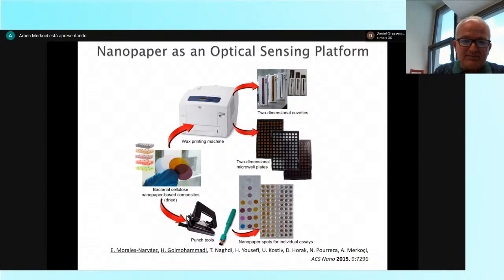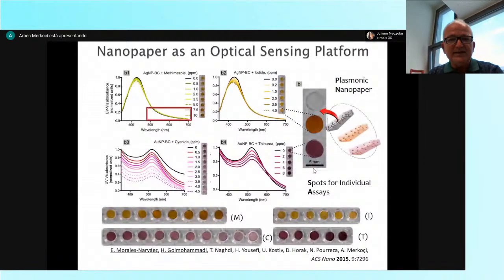So to make some simple optical measurements, we need to set up some cuvettes, like two-dimensional cuvettes or two-dimensional micro-well plates, in a way that we are able then to detect, like in an ELISA, in micro-wells, several papers and do some measurements. And in fact, we did some simple measurements with some compounds, like, for example, methimazole, iodide, cyanide, thiourea. Of course, we chose some compounds that interact with nanoparticles because, through formation of some complex, they are well known to corrode nanoparticles. And you can imagine that if you change the size of the particles due to the corrosion, the plasmonics of them will change. And you can see here clear changes of the color of the paper upon the change of the concentration. So we have a simple device that shows the concentration of these different analytes.